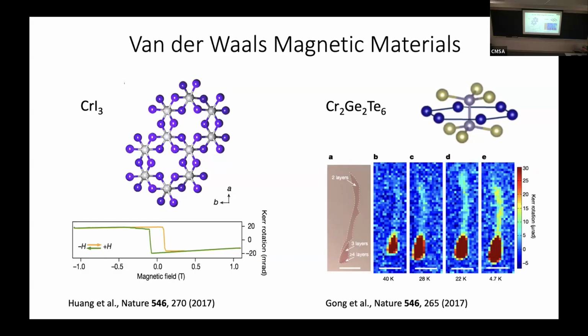And these are so-called MOKE, or magneto-optical Kerr effect, spectroscopy measurements, basically showing that down to one layer of this material you have a ferromagnet, and down to two layers of this material you have a ferromagnet. And this is new and surprising and was discovered as recently as 2017 by Pablo at MIT down the street and some group, I forget the PI's name, on the West Coast.